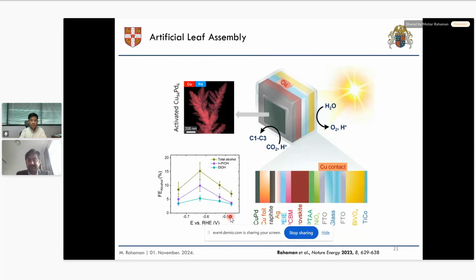and we got a catalyst that worked quite nicely at very low overpotential. Generally, multi-carbon formation happens around minus 0.91 volt versus reversible hydrogen electrode, quite a high overpotential on conventional copper catalyst. We have seen that adding 6% palladium and then activating the catalyst, making it phase segregated, we can even start forming multi-carbon alcohol at minus 0.45 to minus 0.47 volt versus reversible hydrogen electrode. That property allowed us to assemble this catalyst into this standalone tandem photoelectrochemical device.